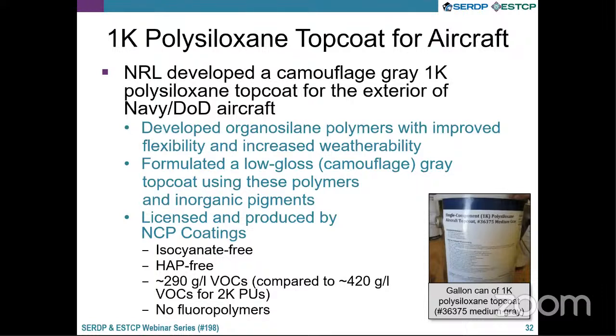Under a different government-funded project, we went back to the laboratory. We took the polymers we developed for the ship top coat and modified them. We increased the length of the backbone, reduced some of the branching and alkoxysilane groups, and modified a few other things in order to develop formulations with very high flexibility, but also good solvent and hydrocarbon resistance, and very good weatherability.